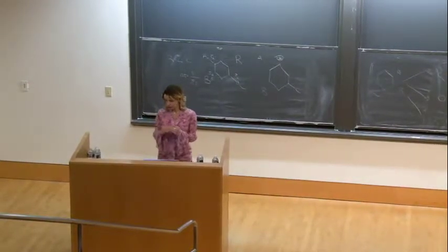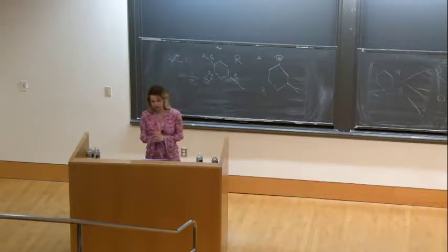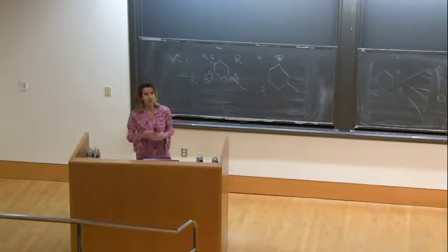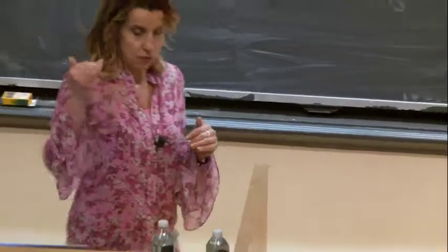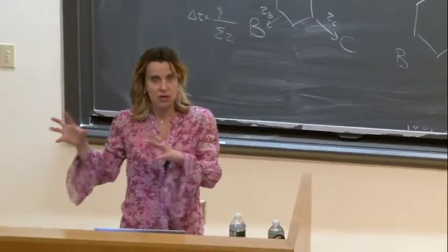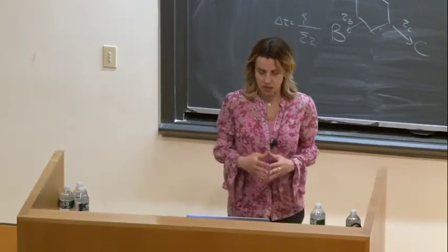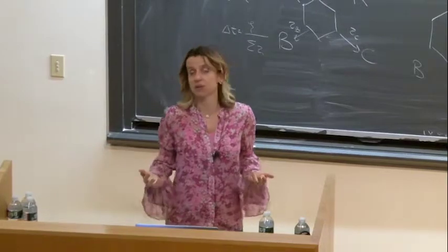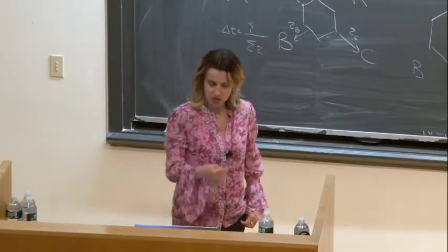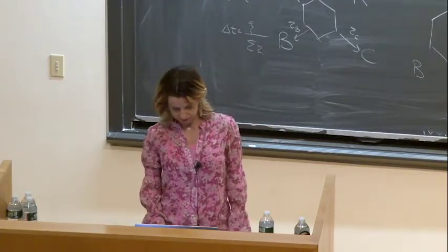When you move to the mechanism for soot, the models for soot, as I was mentioning the first day, it's not a sphere. It's something that is complicated, something that has a morphology, and the morphology plays a role on the rate. So it's not that sphere 1 plus sphere 2 becomes a bigger sphere, but we need to somehow rethink or implement maybe a different rate that takes into account those properties, okay? And again, you go back to the question, what are the properties that you need to preserve to describe the behavior of nanoparticles?